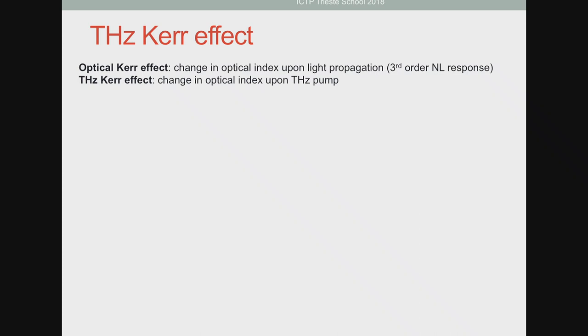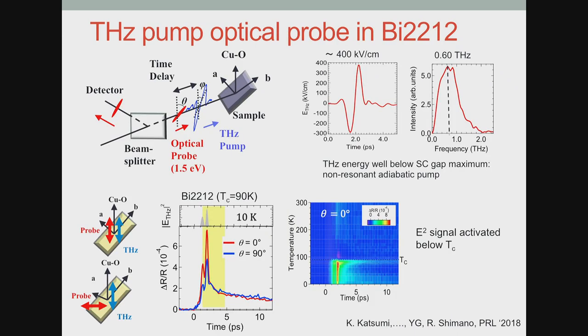Now, this kind of third-order signal is actually, so you heard about the Kerr effect in the previous talk, but historically, the Kerr effect is defined not in the way that was talked about by Aharon Kapitulnik. In fact, if you look at optics books, the Kerr effect, more rigorously, is a change in the optical constants that depends on the light intensity. If you look at your optics equation, you have the optical index, and the optical index is, to linear order, independent of the electric field. Now, if you go to the next order, there is actually a change of the optical index that goes as E squared for inversion-symmetric materials.